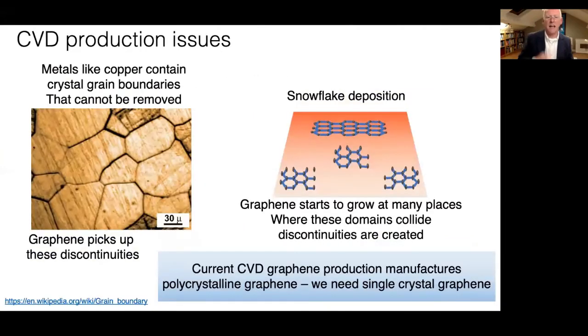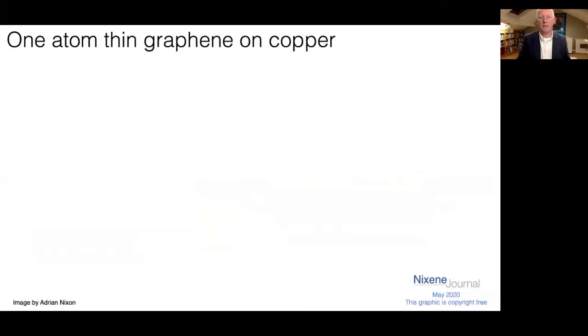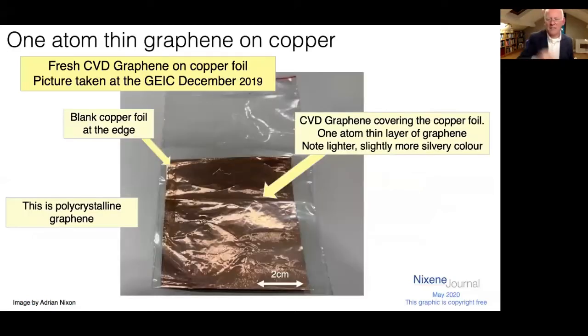That's how it's made. However, it does contain defects. So you have crystal grain boundaries in the underlying metal, and graphene can pick these discontinuities up. It's a bit like trying to grow graphene on crazy paving. And then you've also got this snowflake deposition where the graphene grows at multiple points, a bit like Jack Frost on your car, where the domains collide together. They don't quite match up and you get weaknesses there. And that's called polycrystalline graphene. And this is an example of it.